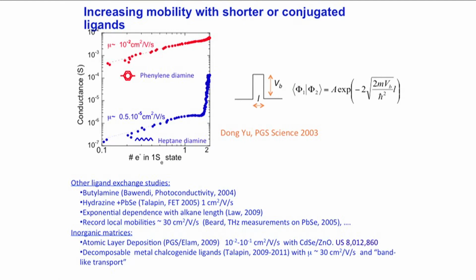And then it was easy to change the ligand to try to see how much one could change the conductivity. This was an example going from an alkane to a conjugated molecule, and you can easily get 2 or 3 orders of magnitude improvement in mobility by adjusting the ligand. And this has been pursued by many other people. The first one to follow was the group of Bawendi, who published photoconductivity studies on this, and they made it clear that it's not so much the need to have some molecule that binds the 2 particles, but just making the particles closer together.